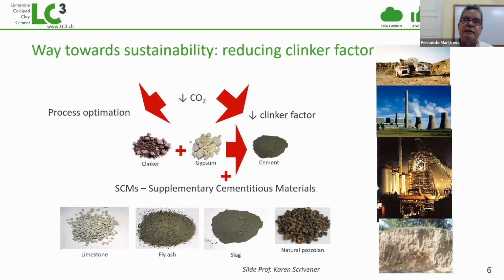And there are several ways, and it's already discussed everywhere in the forums. You can use alternative fuels, you can increase the efficiency of the kilns, but the most practical way, and everybody agrees with this, is to reduce the clinker factor, because clinker is the most energy intensive component in the cement. And there are materials, some of them byproducts like fly ash and slag, that can replace clinker successfully in the cement, and produce the cement with less clinker, therefore less CO2 emissions and similar properties.